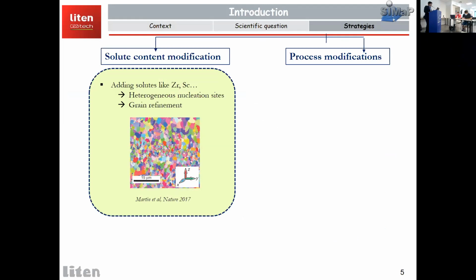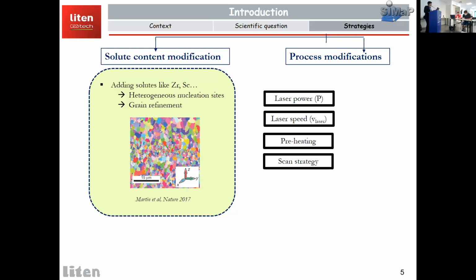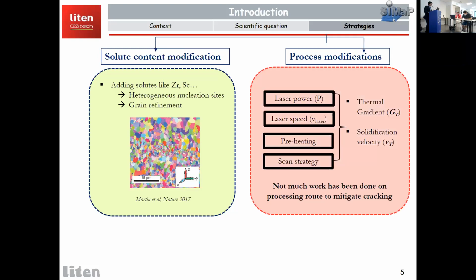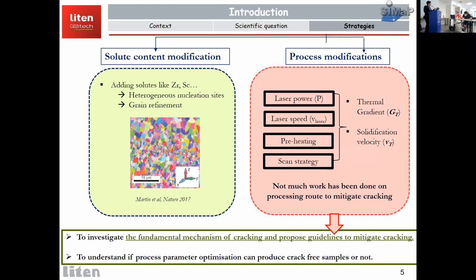The second way can be thought of as process modifications, for example, changing the laser power, laser speeds, the preheating, the scanning strategy, basically to change the solidification conditions like thermal gradients and solidification velocity. But not much work has been done in this part of the strategy. For example, there is not much literature which reports cracking mitigation due to process modifications. So my thesis is focused on this particular aspect of process modifications.